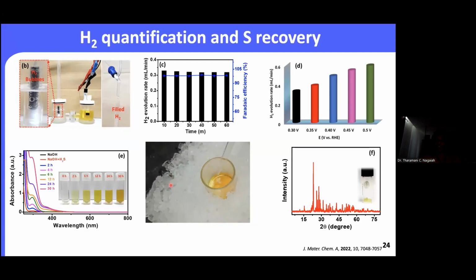Now the question is that, apart from producing the hydrogen here, we are also producing sulfur. That means whatever polysulfide has dissolved in the electrolyte, through the acid treatment, we are precipitating. You can see the yellow color, and we have extracted this material, and the XRD confirmed that the material which has been produced is elemental sulfur.